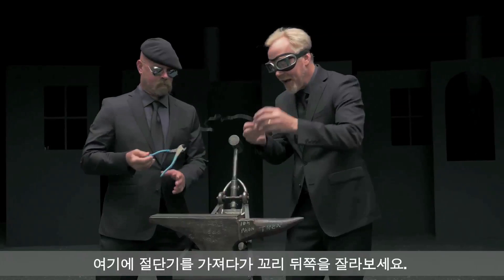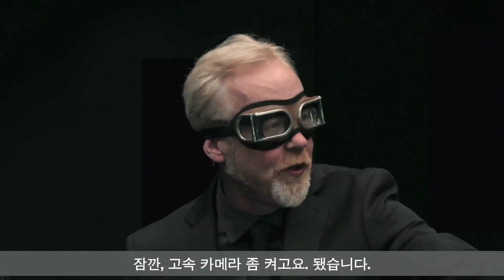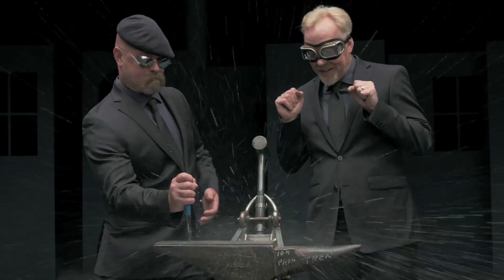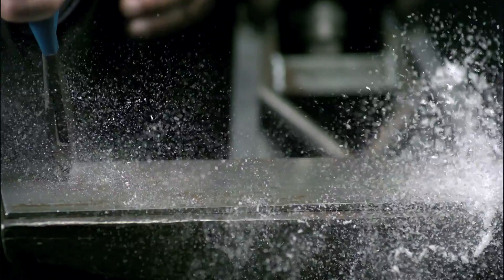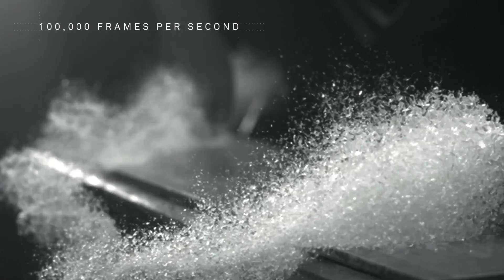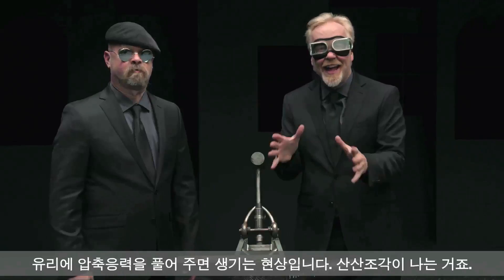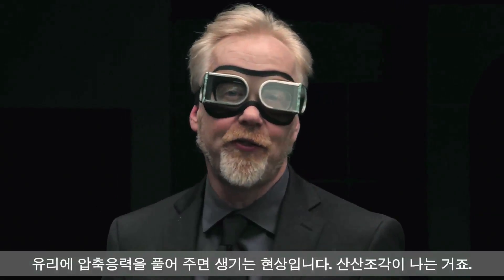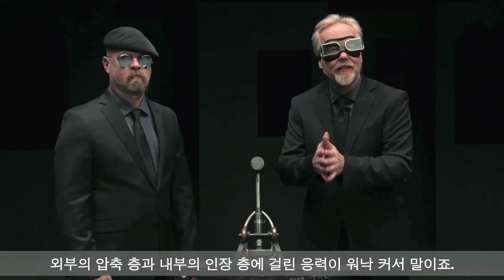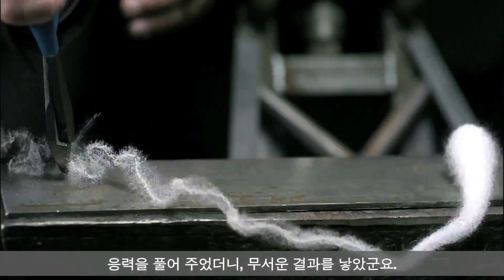I feel like we've been swindled. Swindled not — we have just experienced the power of compressive strength. It does, however, have an Achilles heel. Take those nippers right there and nip the backside of the tail of this Prince Rupert drop — cue the high-speed camera. That was even cooler than I thought it would be. That is what happens when you release the stress in compressive strength glass — the whole thing shatters. Spectacularly. That's because the stress was so great between the outer compressive layer and the inner tension layer that when released, it was a catastrophic result.